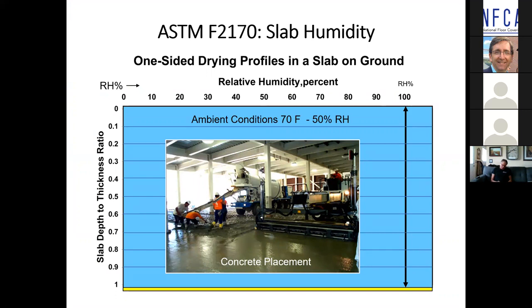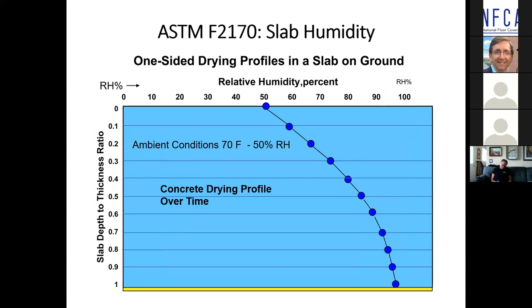So now, over the weeks and months that follow the placement of that concrete, and I want to make a point here, all of these moisture tests presume that there is an effective low permeance vapor retarder directly underneath the concrete. If it's not there, then the numbers you get are all subject to change. So with the vapor retarder in place, directly in contact with the underside of the concrete, not below sand or gravel, it's got to be directly under the concrete, ultimately the surface region of the slab will equilibrate with the ambient humidity, in this case 50%. But as we go deeper into the concrete, the relative humidity increases.